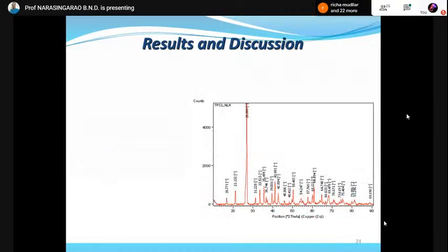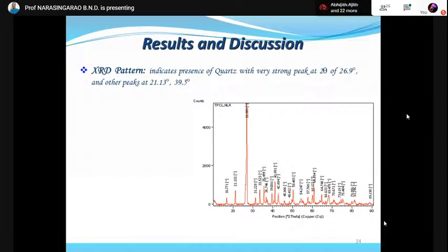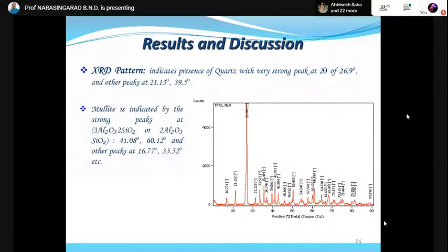And this is the X-ray diffraction pattern. The quartz is indicated by the very strong peak at 2 theta angle of 26.9, and other peaks are also there. Mullite is also indicated by this particular strong peak at 41.08 2 theta angle and other peaks.